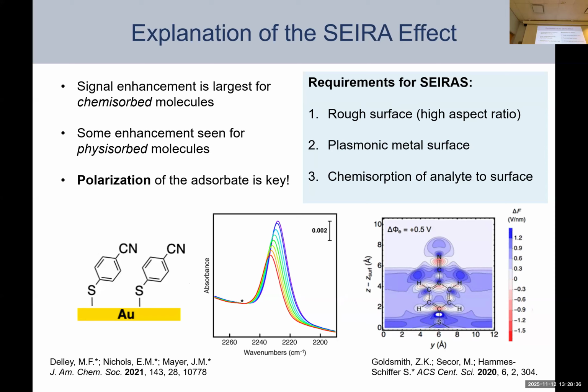And my group routinely encounters this problem that it's actually really tricky to make the correctly prepared film. And I'm happy to talk at length about this in the Q&A if people have questions. But this is a very much understated aspect of SEIRAS, the difficulty in making the correctly prepared film, making it in a reproducible way, and in making it in such a way that it actually survives for the duration of your experiment, particularly in cases where you're evolving gas, like hydrogen or CO bubbles.